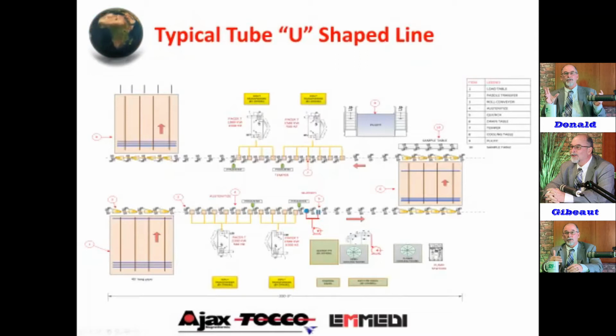There's another factor here that you've got to consider, and that is what we talked about in the basics of hysteresis that happens above the magnetic or below the magnetic Curie point. The other element of that is below the magnetic Curie point, the depth of penetration is very shallow. And after it bridges the magnetic Curie and becomes non-magnetic, typically in this second section coming out of this first one, the reference depth of penetration gets 4.5 times deeper. You lose the hysteresis heating efficiency, so you lose a little bit of efficiency after the magnetic Curie, but you definitely gain that depth of penetration, which helps you on your delta T, the uniformity.